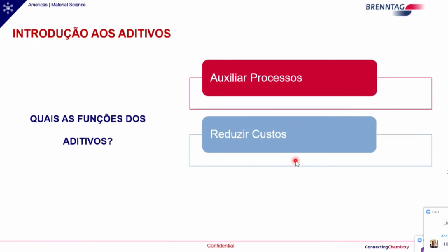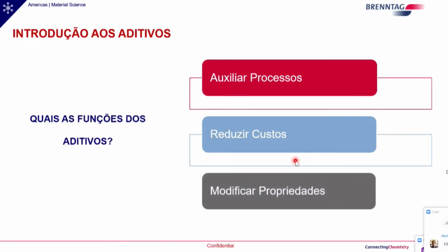Well, the reinforcement filler should have a very good interaction level with the polymeric matrix, so that the fillers do not interfere that much. They should not, for example, cause a significant reduction in the mechanical properties of our materials. So we should be attentive to that as well. And then finally, the modification of properties, which is what we are discussing here today, right? We have polypropylene, which is widely known as a commodity, and its mechanical properties are regular properties. We are able to further improve the properties by adding additives. We add, for example, reinforcement agents, we can use fibers or mineral fillers, and then we are able to enhance the potential benefits by adding this reinforcement agent.